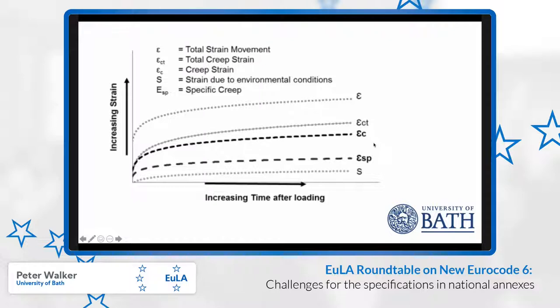And then in the second case, there are other movements of the specimen which we measured in our control specimen. So there's an ongoing shrinkage of the specimen. So we have corrected the total creep strain to the creep strain here, epsilon C, marked by this bold line, by deducting the environmental or the shrinkage movement.